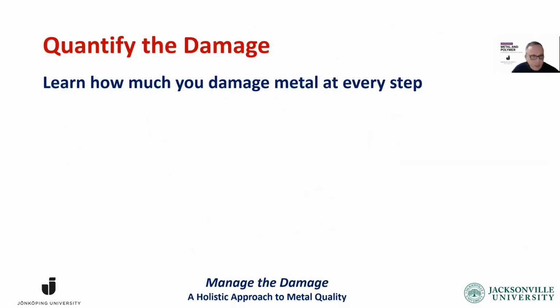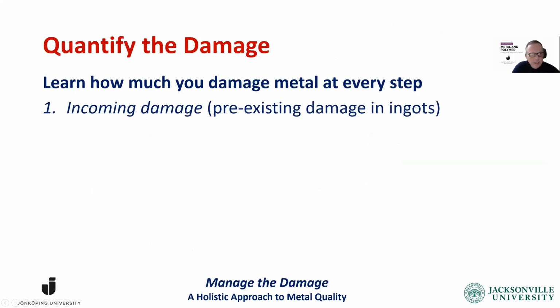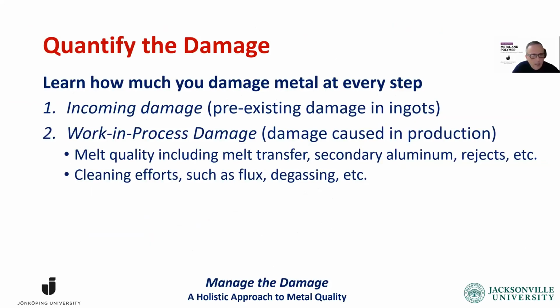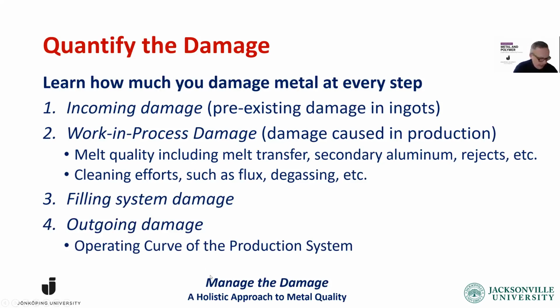So how do we quantify the damage? We have to try to learn how much damage we give to the metal at every step. First of all, what is the incoming damage? How much damage are you paying for when you buy ingots? Then the work in process damage that we cause during production. How much damage are we causing in the melt transfer when we add secondary aluminum rejects? And what I call cleaning efforts, I'm not sure that it's cleaning, such as flux, degassing, etc. Filling system damage, and then finally the outgoing damage.